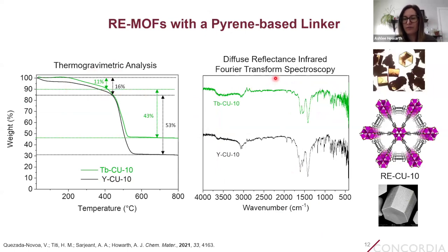And we can use diffuse reflectance infrared Fourier transform spectroscopy to see the different IR active functional groups in the MOF. And we do see a small peak around 3,700 wave numbers, which confirms that at least some of the bridging ligands in our cluster are bridging hydroxyl ligands, even though most are probably bridging fluoroligands.